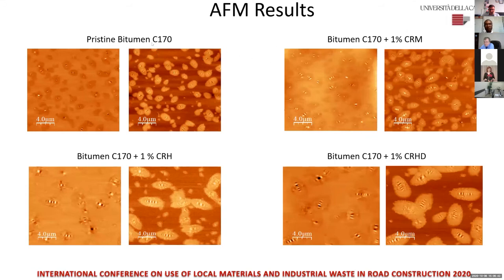from the pristine bitumen of the C170, which is the soft bitumen, you can see here, this is a topographic image of the atomic force microscope, and this is a phase image. They are similar, it's just phase contrast and this is topographic. With the topographic image, we see that these little domains here are the asphaltenes, the hard part of the bitumen, which confirms the colloidal model of bitumen.